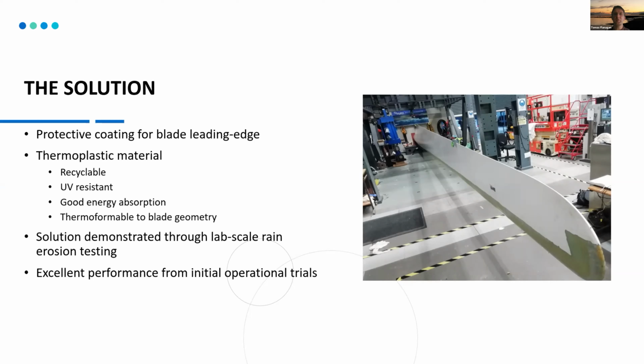The adhesion between the protective coating and the substrate is a challenge. There are some protective materials that are good in terms of stopping erosion, but you need to be able to get them to stick onto the blade. And the shock waves from the impacts from raindrops are passing through into the substrate. If you have different materials, you're likely over time to get deterioration on that interface. So we were looking at those kinds of things and at existing solutions that are used commercially, trying to figure out whether there are opportunities to improve.